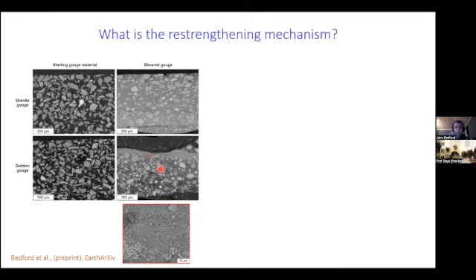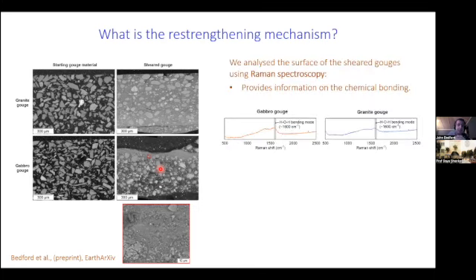But what causes restrengthening? There are two prevailing hypotheses from laboratory friction experiments: that either at frictional asperity contacts within your fault or in the gouge layer here, you get an increase of the real asperity contact area, or you're potentially getting some sort of chemical bonding effect, which could be restrengthening your asperity contacts. So what we did is we analyzed our sheared materials using Raman spectroscopy, because Raman spectroscopy actually provides information about the chemical bonding state of the surface of your sheared materials.